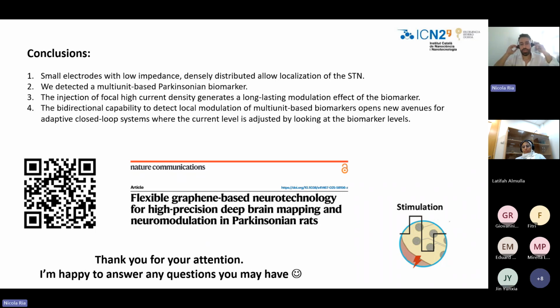So you're asking if by injecting high current, the device loses stability over time? Yeah, the stability of the electrode during the electrical stimulation. At the moment we performed some tests of long-term stimulation, and we observed that it's possible to inject up to 2 billion pulses with a stimulation protocol that injects 1 millicoulomb per centimeter square of charge. So the stability is quite good.